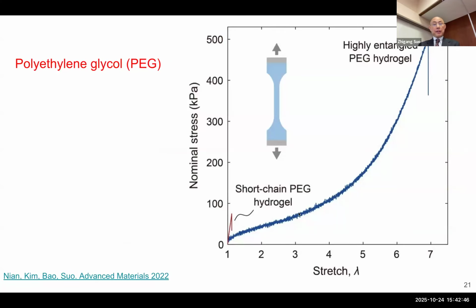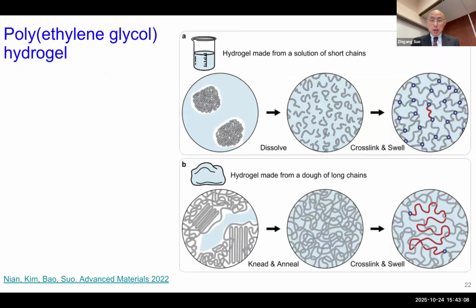And now you can see the difference. This is a regular hydrogel. The strength is very low. It's very stiff because the crosslink is very dense. With this highly entangled PEG hydrogel, you can see the strength is much higher, and it's very stretchable. It's a totally different class of material now. You open up applications.